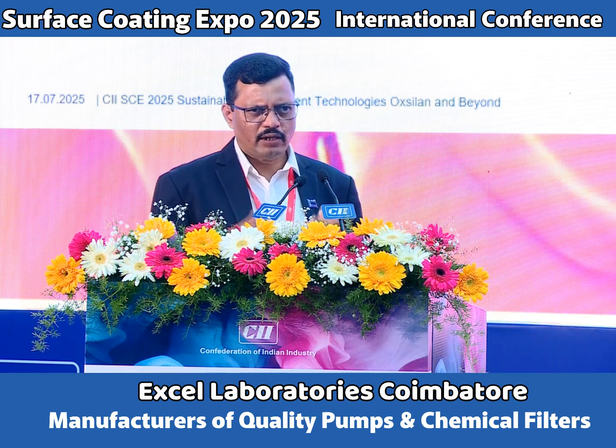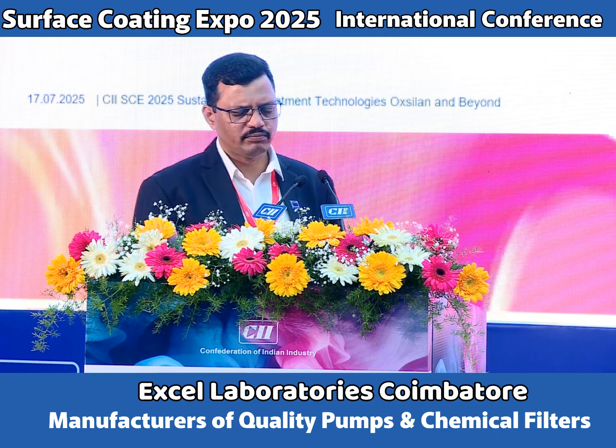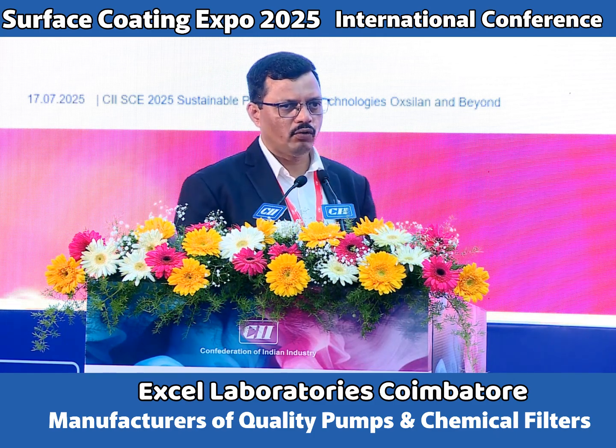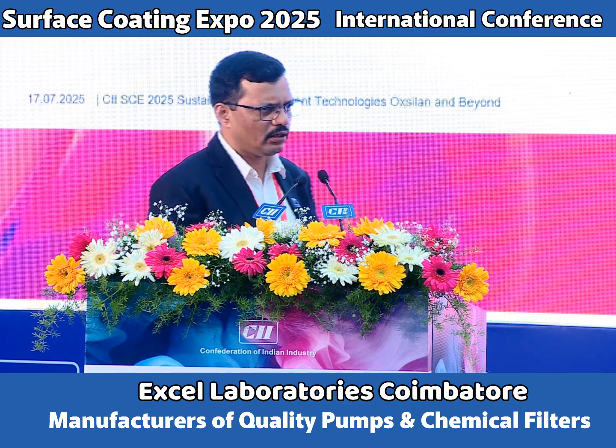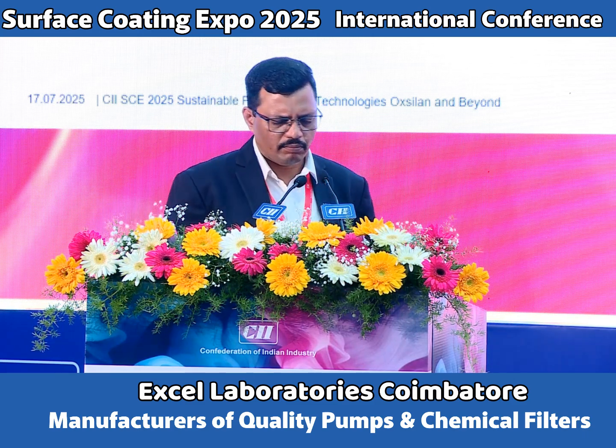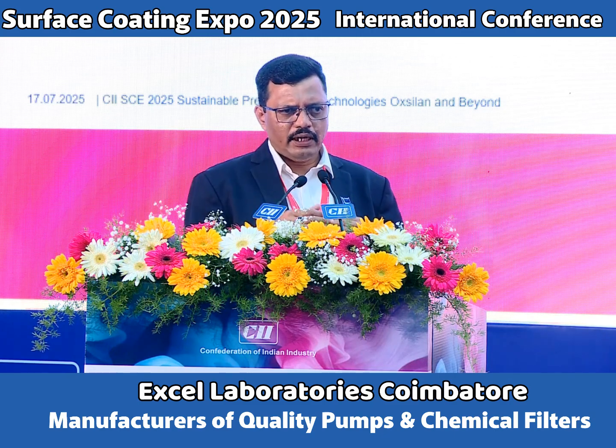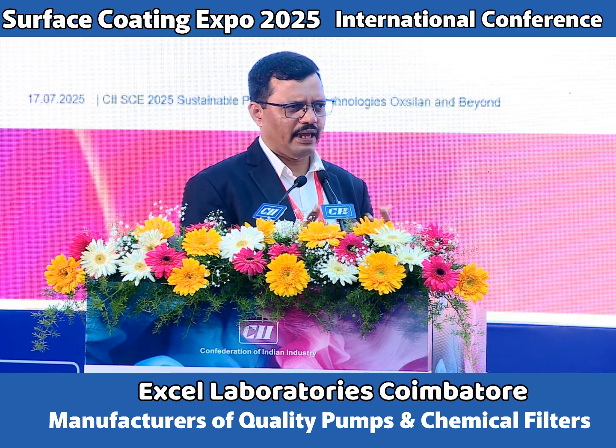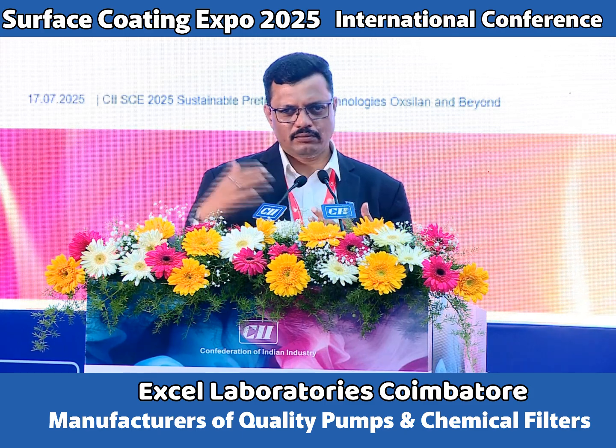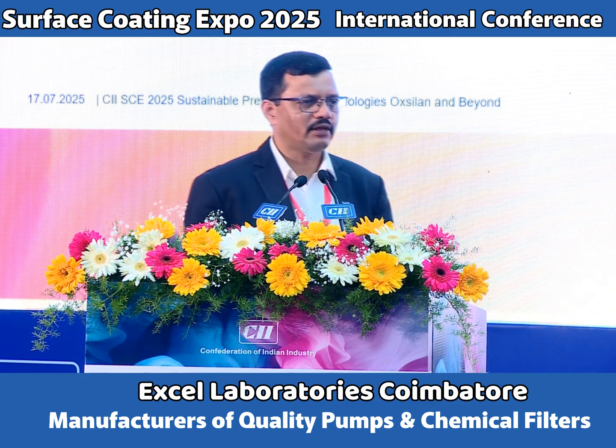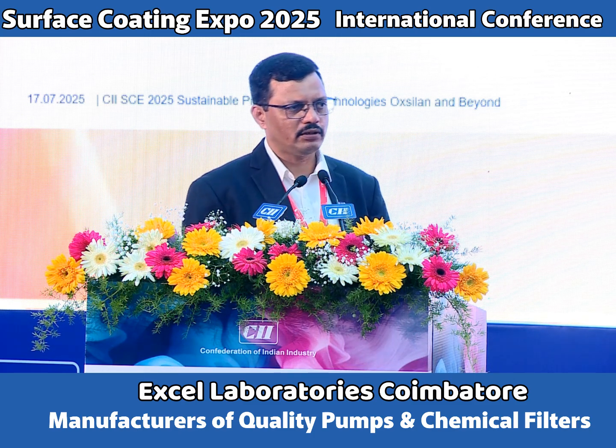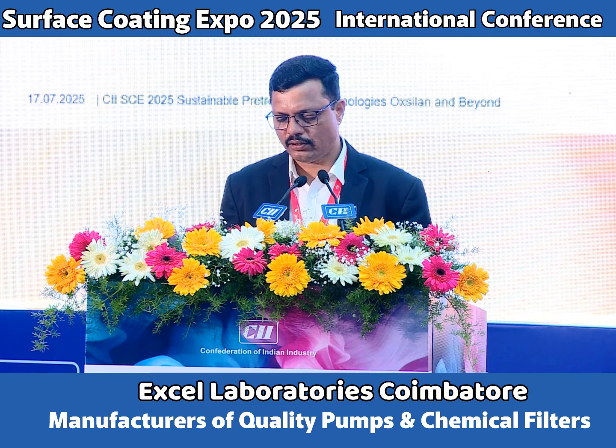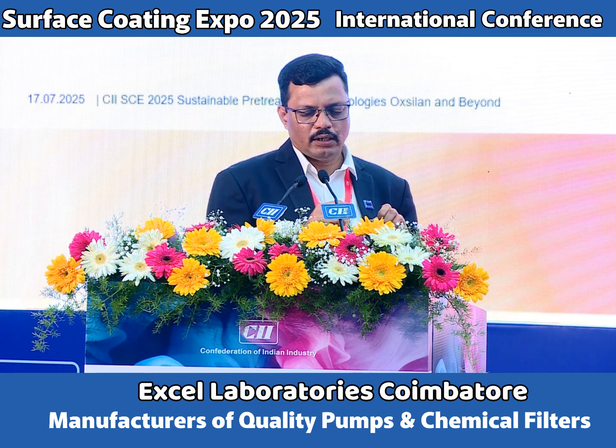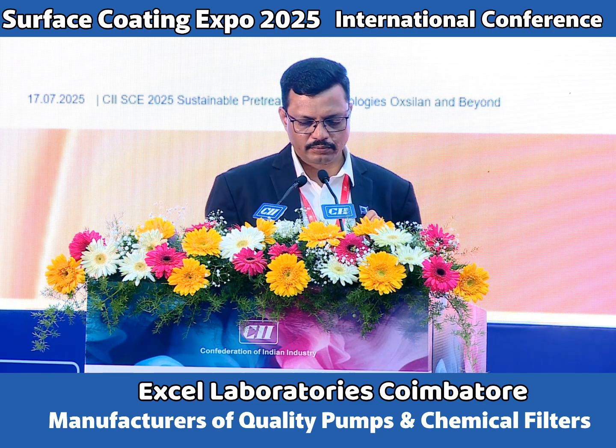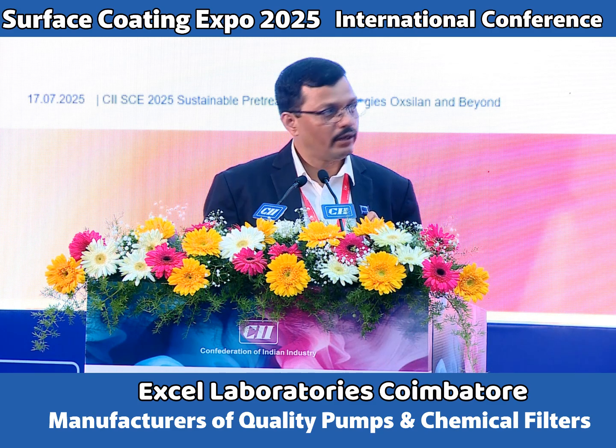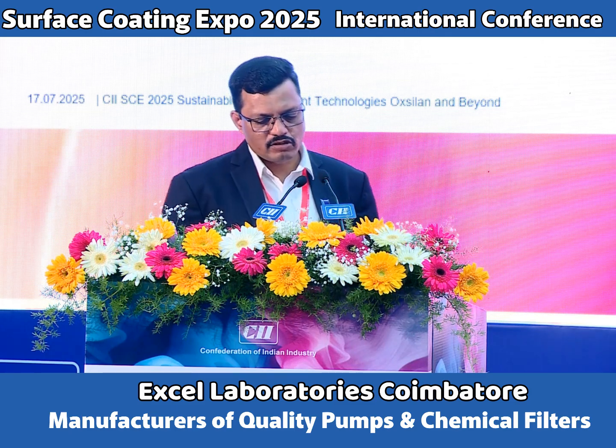And the same organosilane, we use it in our pre-treatment, which goes along with the zirconium hexafluoride, the zirconium inorganic material. And during the reaction, the first reaction is etching of the metal, like in other conversion coating processes. So here also in the thin film process, the first reaction is etching of the surface, and there is a formation of a highly resistant zirconia matrix. I'll just try to see whether the pointers are working or not. Okay. So, a highly resistant zirconia matrix.